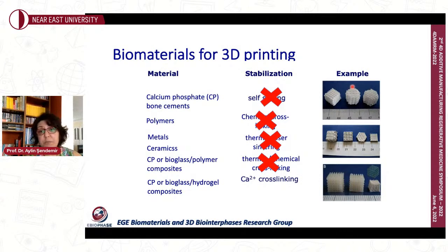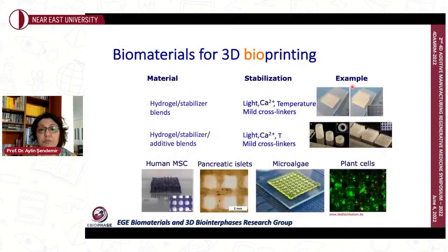But still, to keep hydrogels intact, we need to use some type of cross-linking. And because we need to avoid chemical cross-linking, usually calcium cross-linking, in the example of alginate, for example, or some different types of light cross-linking methods are applied for bioprinting. So when we look for biomaterials for 3D bioprinting, we have hydrogels with different stabilizer blends, and hydrogels and possibly ceramics, or sometimes we even read about, for example, magnetic nanoparticles, so different composites of hydrogels with either calcium cross-linking or temperature cross-linking.